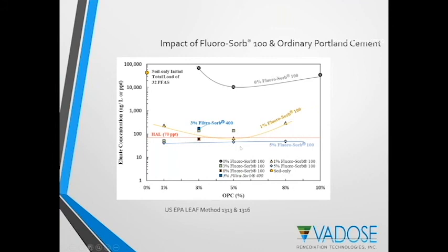heat of hydration. When we blended Fluoro-Sorb in at as low as 1%, Fluoro-Sorb 100 with these various different portions of Portland cement, you can see that we were getting significant improvement in the leachability of these PFAS compounds. And at one formulation, 5% Portland cement, we were able to be below the health advisory level of 70 parts per trillion. But again, we see that effect where it tails upward again when there's an increase in Portland cement. And then finally, the blue line represents a 5% Fluoro-Sorb addition, and you can see in all cases that we were able to achieve results below the health advisory limit of 70 parts per trillion. So that was a pretty positive demonstration that Fluoro-Sorb would effectively reduce the leachability of these PFAS compounds from that soil.